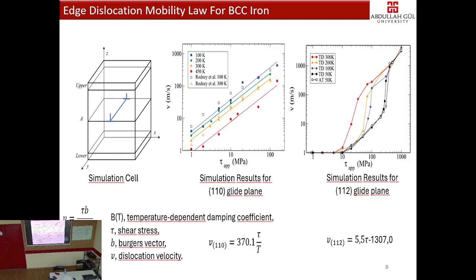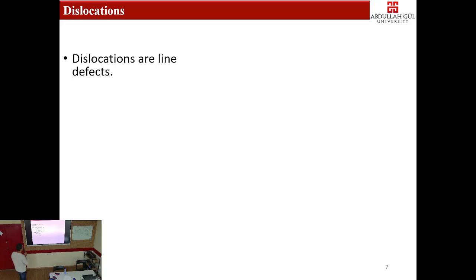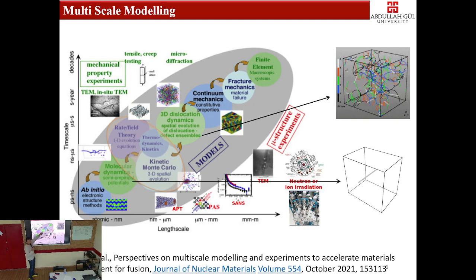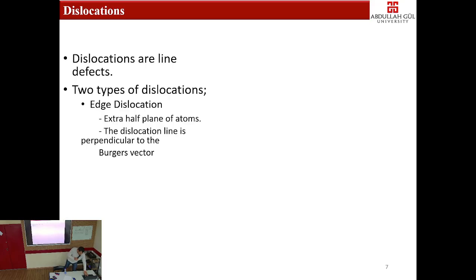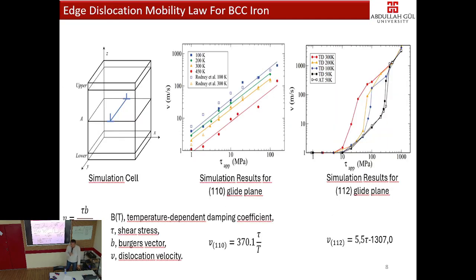If we want to study hydrogen embrittlement with 3D dislocation dynamics, we need a mobility law for edge dislocation. But if we use that mobility law, it is only a function of temperature. We need the effect of hydrogen on that mobility law. That is why we had an idea. Why don't we simulate everything with MD to calculate the effect of hydrogen on both the drag coefficient and also the shear stress, because the pinning stress, the critical resolved shear stress, will also depend on hydrogen.